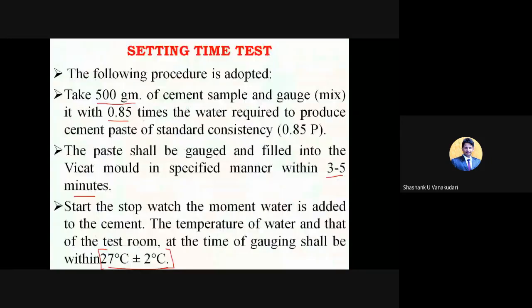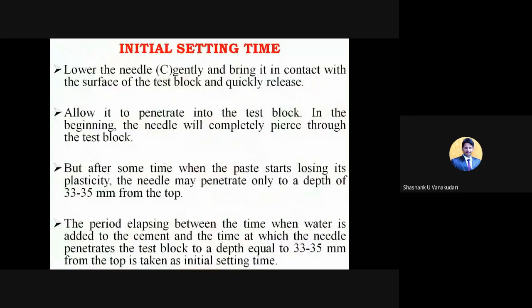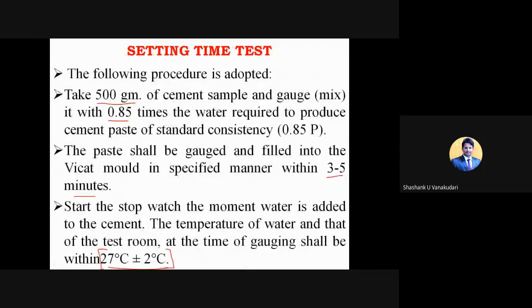Clear? And then allow it to penetrate into the test block. In the beginning, the needle will completely pass through the test block. But after some time, when the paste starts losing its plasticity, clear? The needle may penetrate only to a depth of 33 to 35 mm from the top. I showed you in this, right?